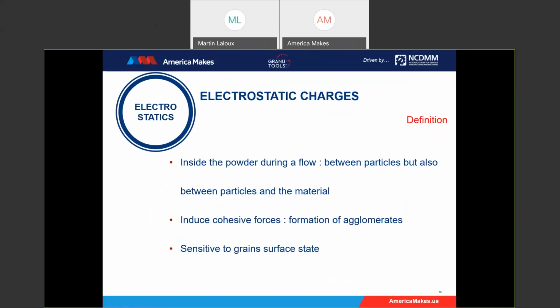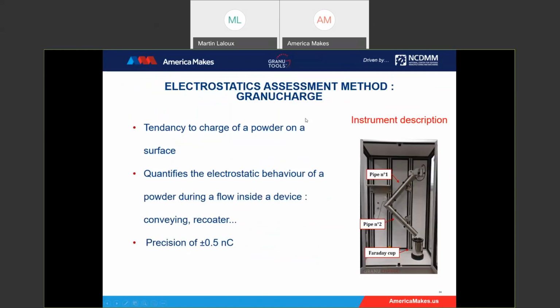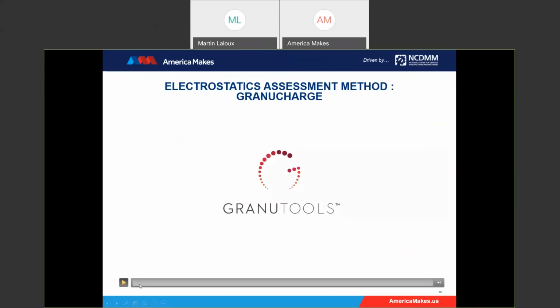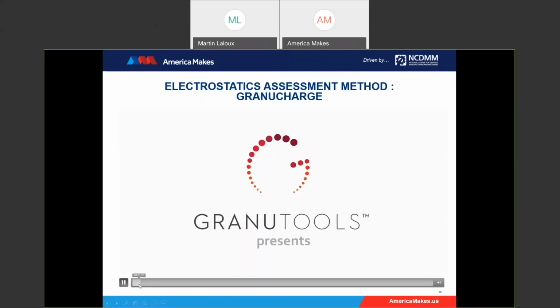Then we took a look at the electrostatic charge. Inside the powder, there is a flow between the particles, but also between the particles and the material, and it induces cohesive forces. I will explain the instrument description again. Here we have a box, a V-tube in stainless steel, and a Faraday cup to measure the charge. The precision of this device is roughly plus or minus 0.5 nanocoulomb. Again, the video of the device will make it easier to understand what we did in the study.